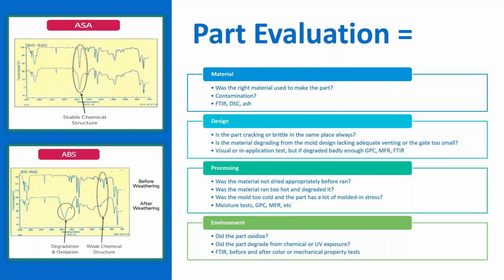And then for your pictures, you can see an ASA compared to an ABS. And so before and after weathering, you can see that there's an additional peak now where you're starting to see degradation of the material in the ABS because it degraded. So those new bonds that are forming from the degradation, it's apparent in the FTIR. And so that's where you can see your difference between them. And you can see that the ASA has a stable structure and does not show the same bond formation in the degradation and oxidation section of the ABS.